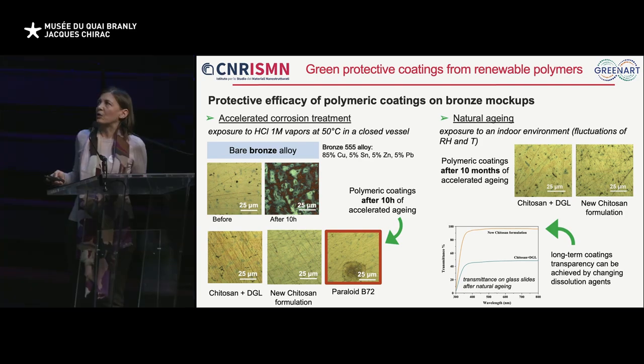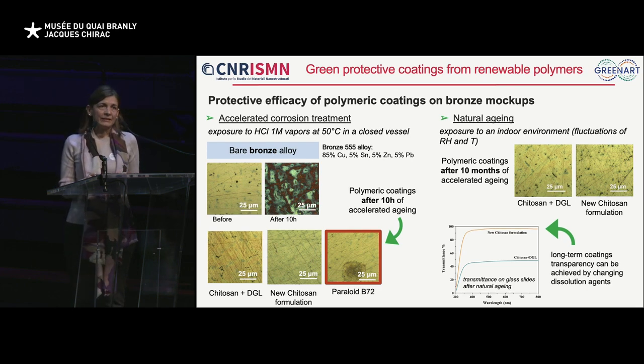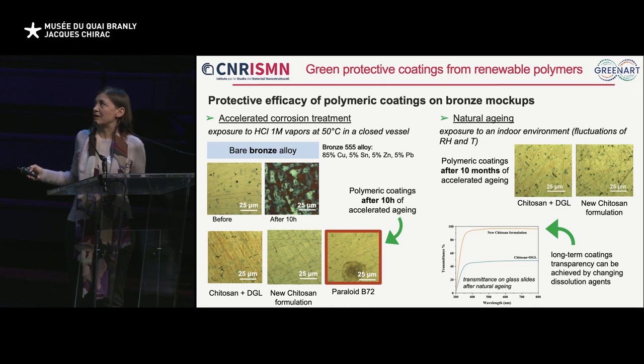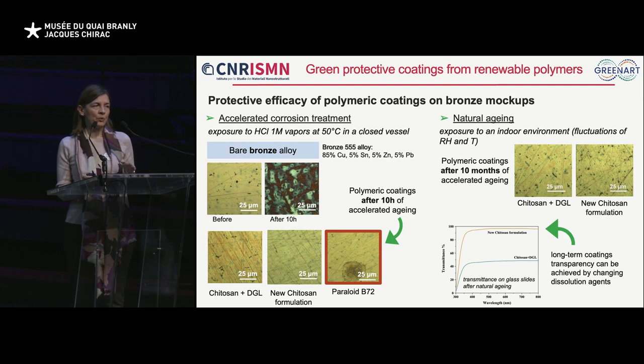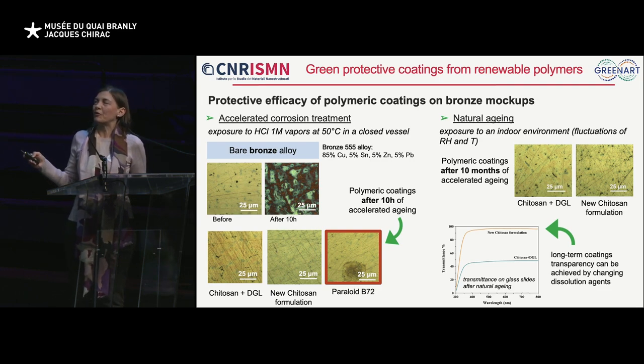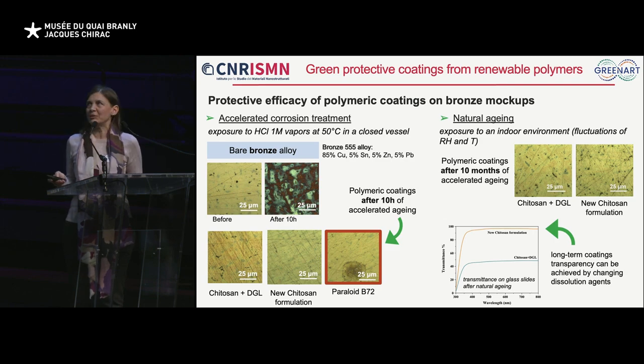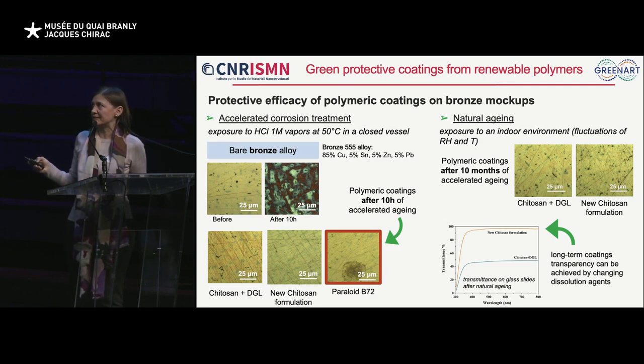Both the other formulations are quite stable, but if we look at the aging treatment performed up to 10 months, in this case we observe by transmittance measurements that the new chitosan formulation has significantly better long-term stability, because in the previous formulation we observe after 10 months a loss of transparency. It is worth noting that in this case we are using only formulations based on biopolymers without any corrosion inhibitor. So we want to avoid in the first step the use of corrosion inhibitors. And also in this case we have a very good stability.